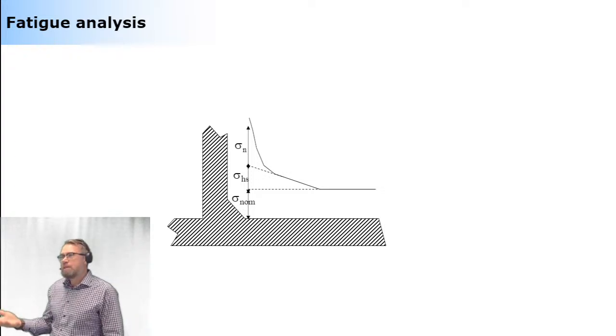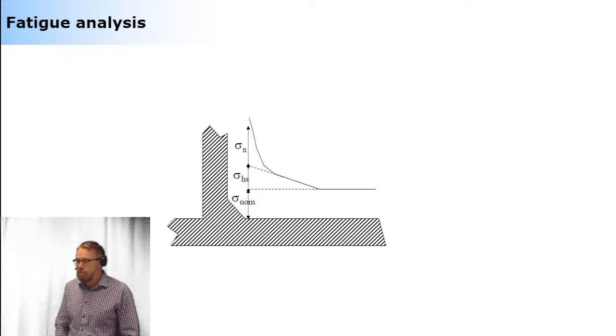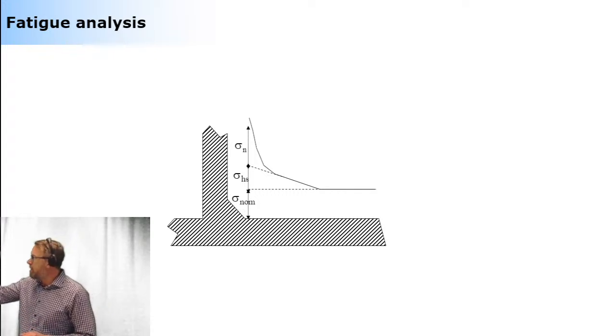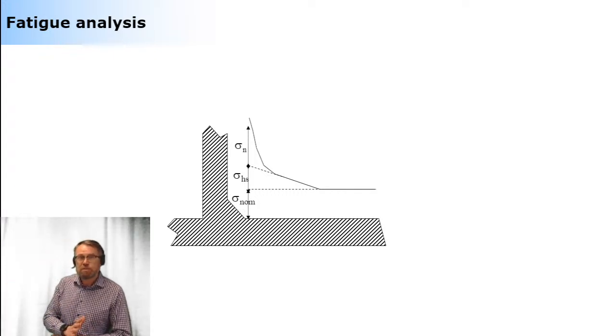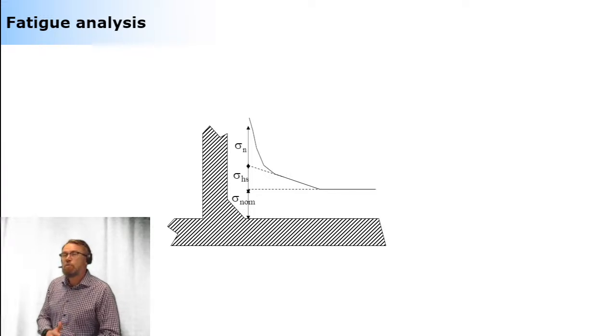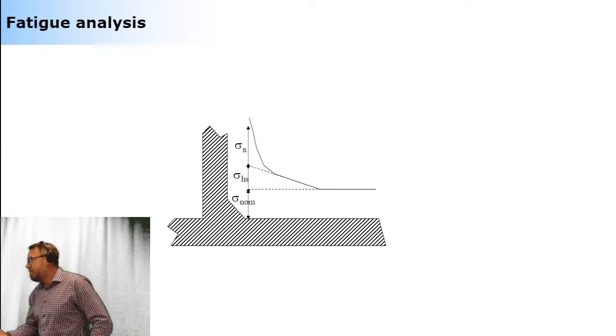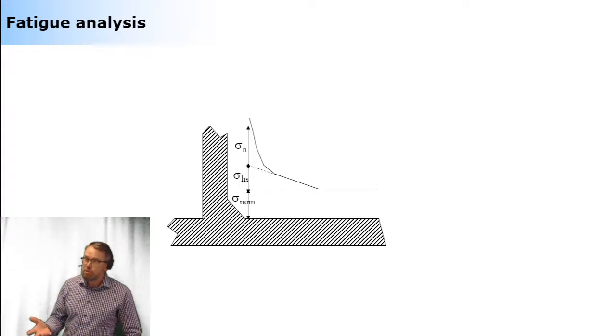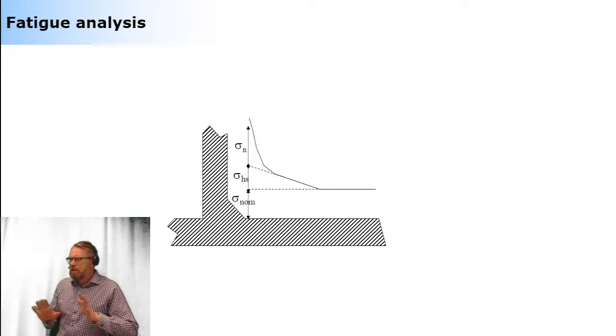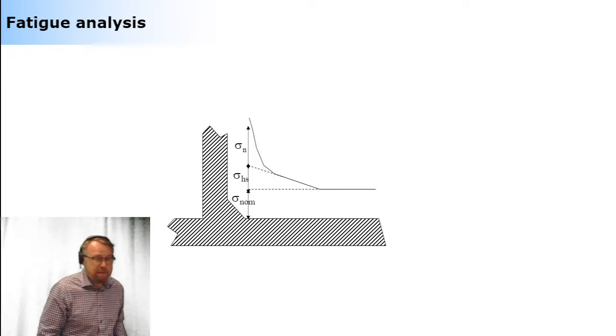Now, based on the method you use, there is a method that I think this university is very advanced in, and Professor Timo Björk, I don't know if you have met him, you haven't. He's specialized in fatigue, and they have developed a method where you can take something that is not exactly the actual stress that is going to apply in a weld toe, but very close to that. It's called hotspot stress. And with this hotspot stress, you can use a more advanced, more enhanced fatigue life prediction. Or you can actually get the actual stress that is applying, and then you can use fracture mechanics. Not easy to use because it needs a lot of parameters that sometimes are not so clear, but that's one possibility. All right, but first things first. First thing would be this.